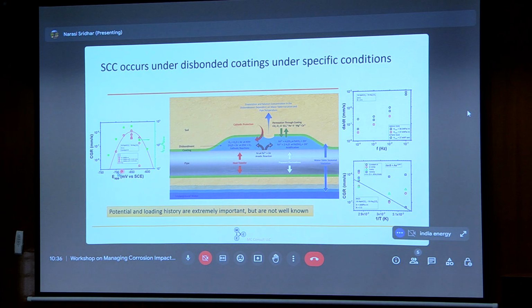And what is known is that the crack growth rate is a critical function of the potential, so it occurs only in a narrow potential region. So in this area, the potential is much more negative than minus 750, there should be no cracking, whereas in this regime, there is cracking. And of course, the crack growth rate depends on the frequency of loading, which depends on the pressure cycles, how fast the compression occurs in the gas stream. And it also depends on the temperature, because from the compressor, there is an adiabatic heating of the gas, and the temperature rises near the compressor station, and the crack growth rate can increase.